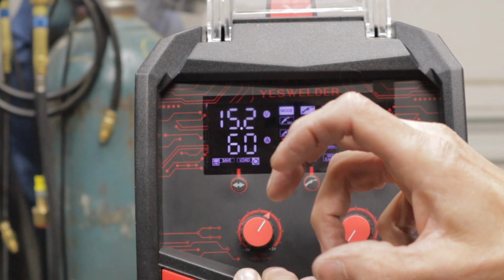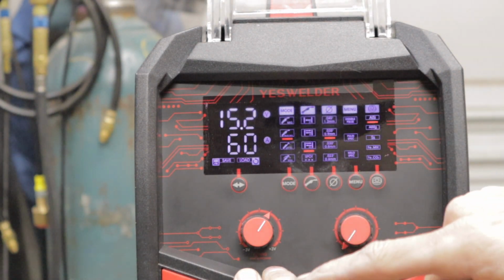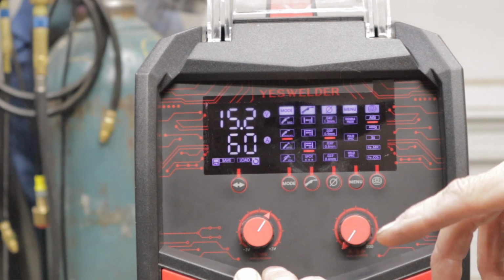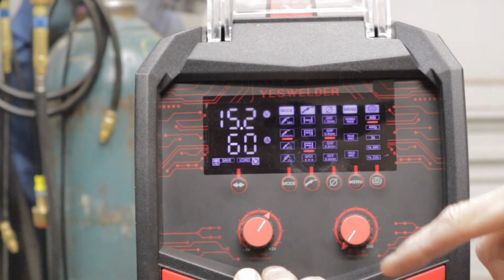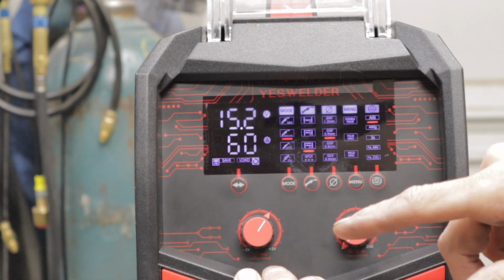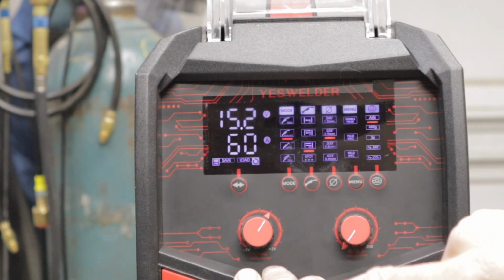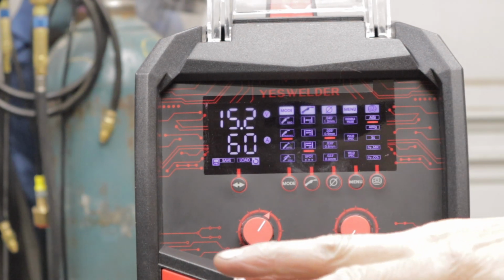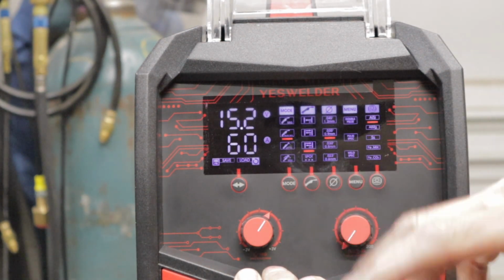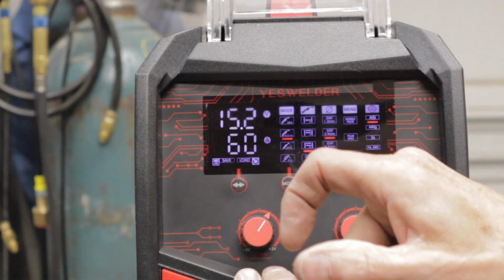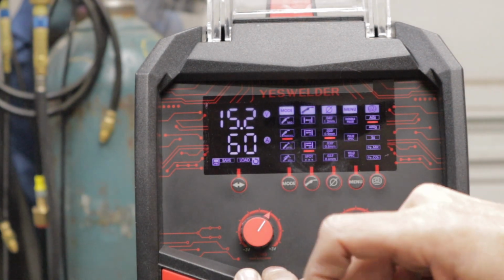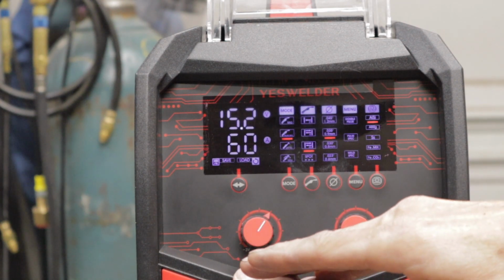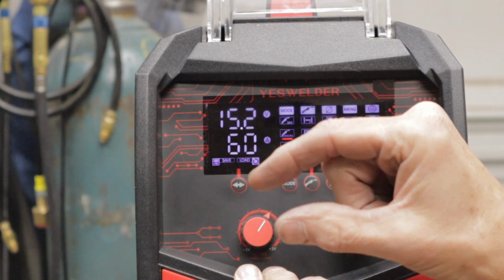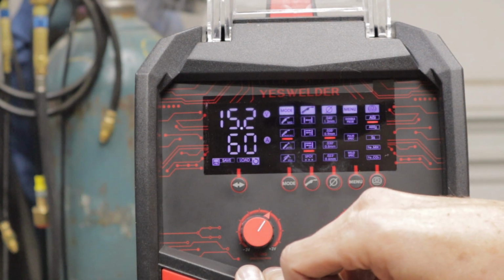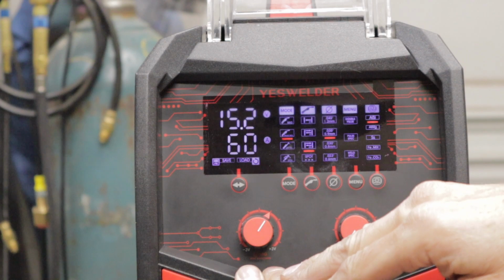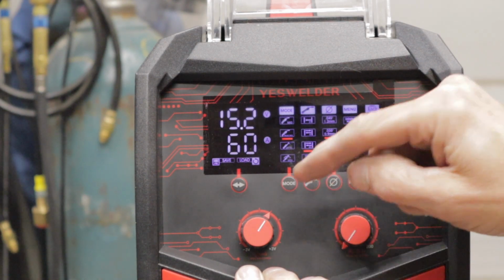so that it's perfect for the start, a few inches in, 2 or 3, 4 at the most usually if it's thicker material, that amperage now, the heat has begun to run ahead of your gun, and you either stop because it's going to burn through, or it does burn through. And so you're only capable of actually welding very short areas. It's either that, or you set your amperage perfect for that long weld, and the first inch or two until the heat builds up in the metal is very cold, and so you don't get a lot of penetration, and there's no real strength at that beginning of the joint.